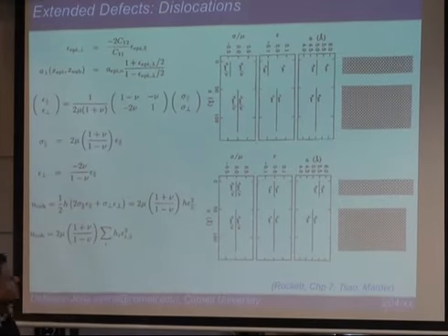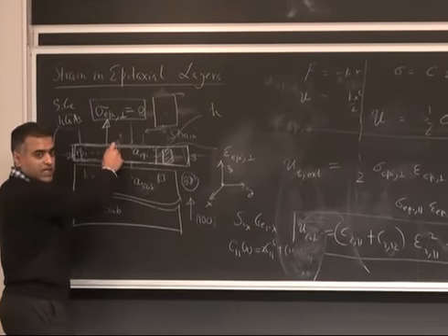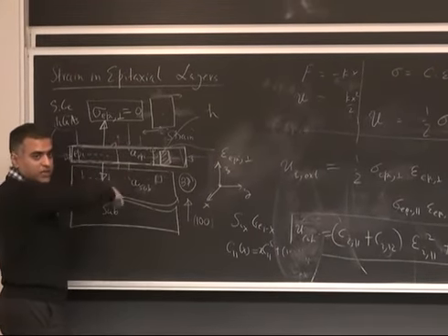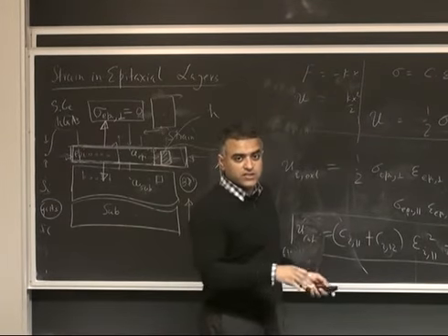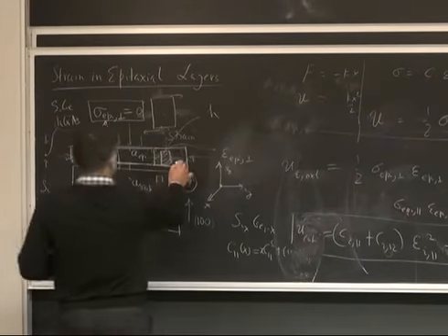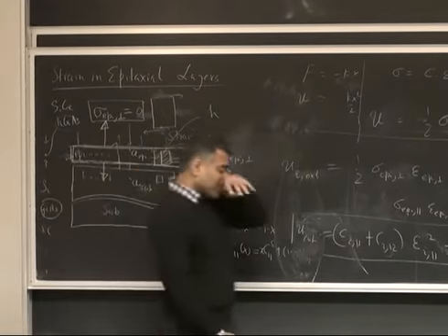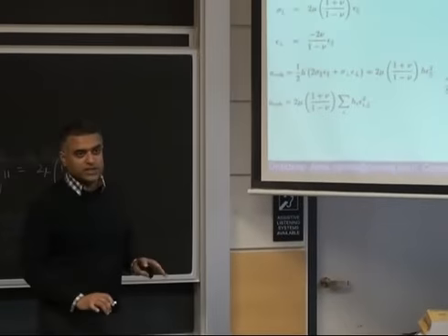You can sum it, but then very importantly, if you have a continuously changing layer, meaning instead of a uniform composition alloy, I have a graded alloy. I start from gallium arsenide and I start grading it to 30% AlGaAs, and compositionally I change it linearly, parabolically. Then you integrate this coherent strain, instead of summing it over each layer. So the I is kind of a thin slice here, and then you can start adding it. And now the graded layers are very important in III-Vs because they allow you to do quite a bit of tricks with dislocations and preventing them and that sort of thing.